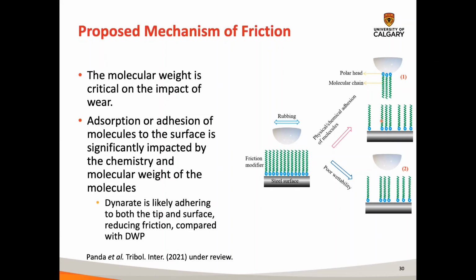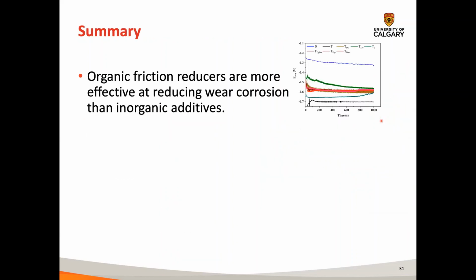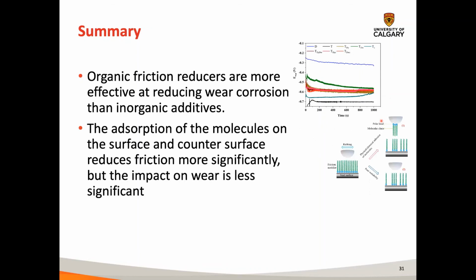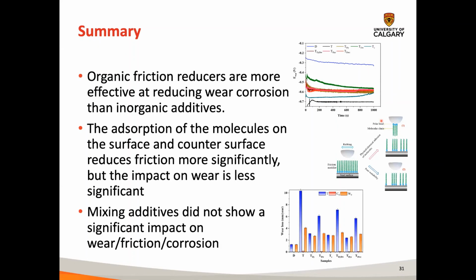Right. So we think that Dynarate is sticking to both the counter surface and the substrate compared to DWP, and that's why we're seeing this sort of benefit from this additive. So to summarize, we see that organic friction reducers are more effective at reducing wear and corrosion than the inorganic additives. We looked at the mechanism, and mixing the additives didn't really show any impact on the wear, friction, or corrosion rates.